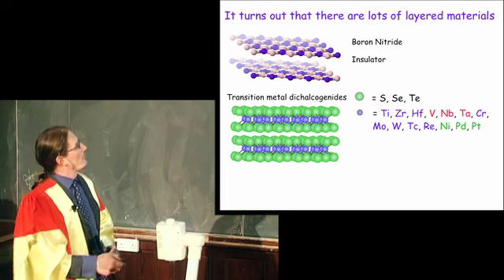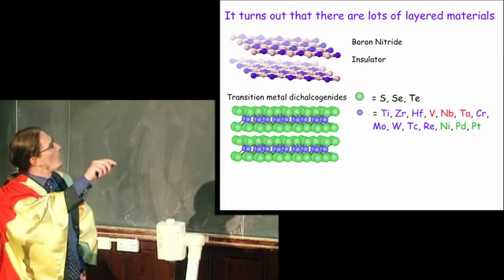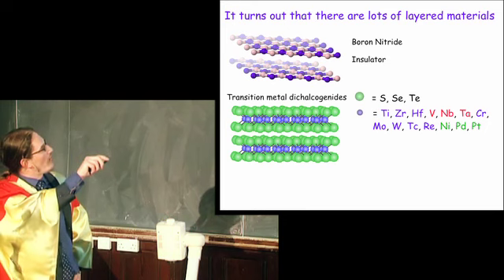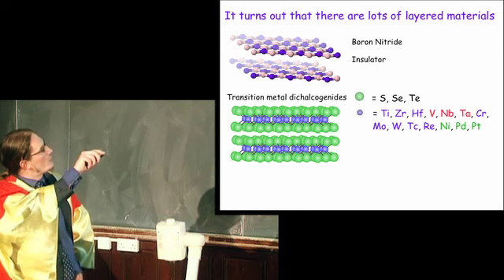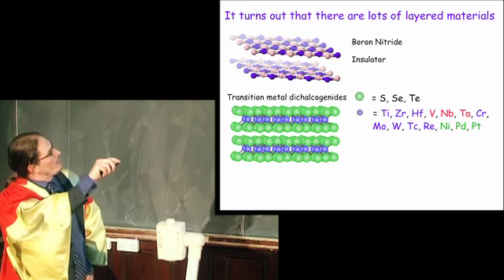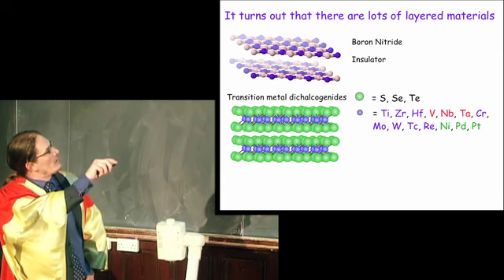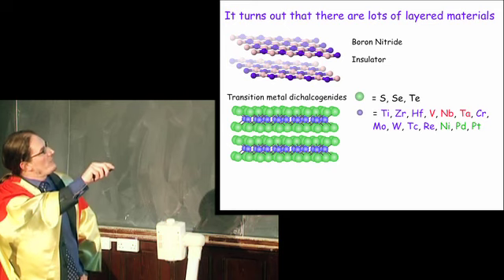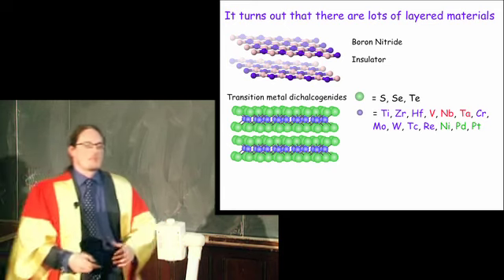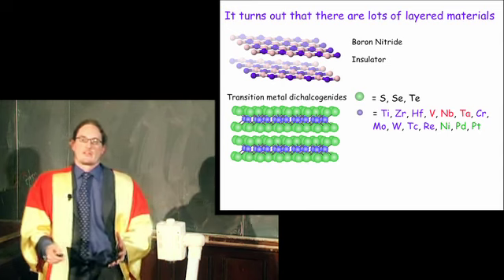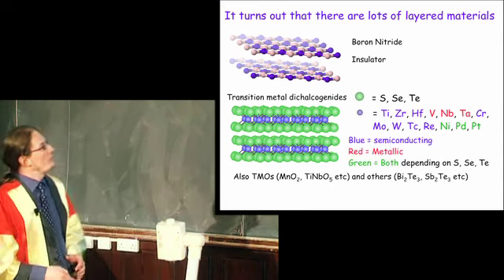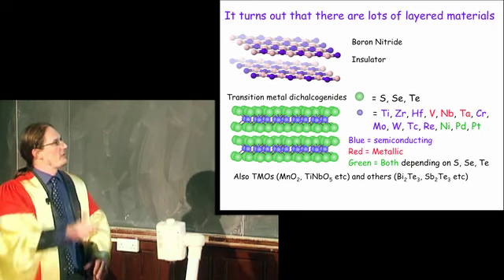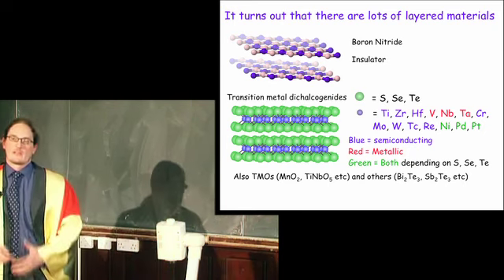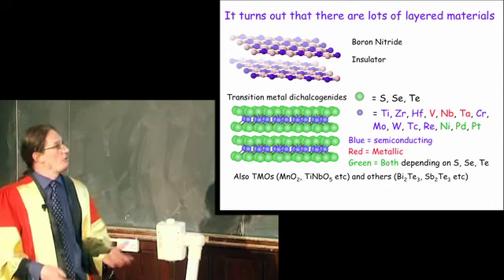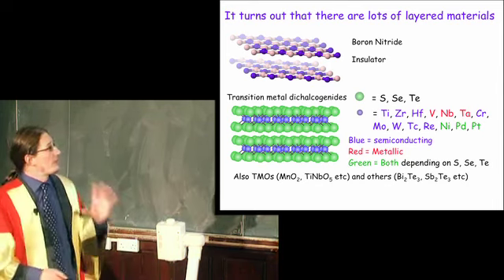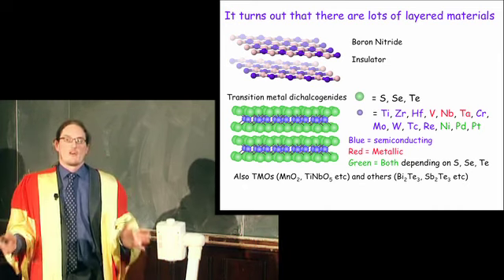There's also a family of materials called transition metal dichalcogenides, which also are two-dimensional layered structures, except they're like a sandwich of two different types of atoms. The outer atom can be sulfur, selenium, or tellurium. The inner one can be a range of transition metals. There are about 15 candidates here times 3 of these, which means that there are nearly 50 possibilities for these transition metal dichalcogenides. That's useful because depending on the combination, these materials can be metallic or semiconducting. The semiconducting ones have band gaps that vary from about 200 meV up to 3 eV. So these materials fulfill the entire gamut of material properties.